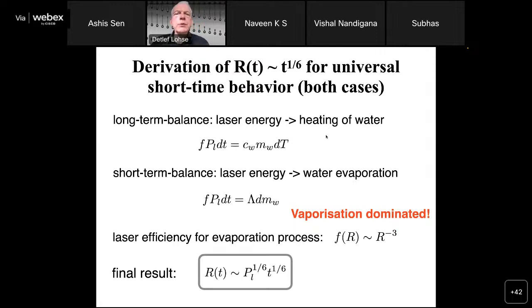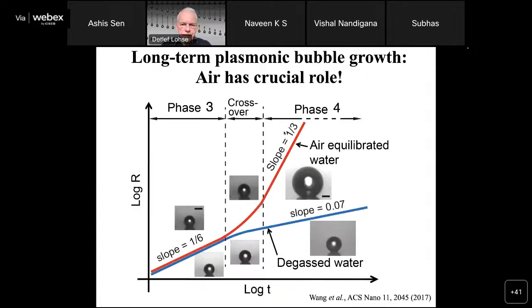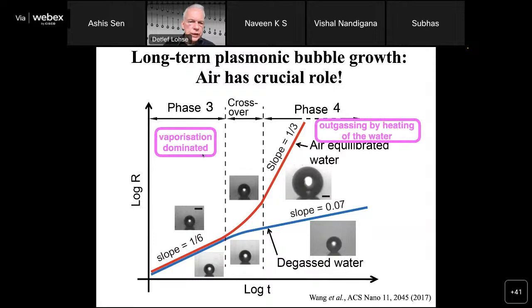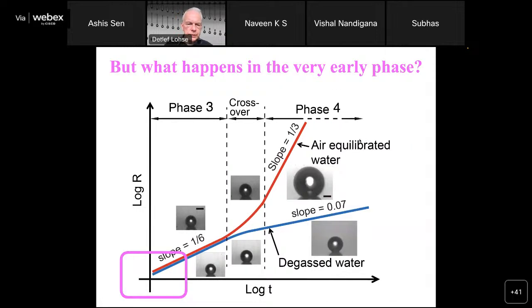So the question is, where do you use your laser energy for? Well, in the long term, it's for the heating of water, but in the short term, of course, it's for water evaporation, and then you get that the radius goes like t to the 1/6. This is this phase around here. So at early times, the radius goes like t to the 1/6, and then later for water with gas, the radius goes like t to the 1/3, or it's about constant if there is no gas. But the big question is now, what's happening? Well, this is what I explained to you. Here it's vaporization dominated, and here it's dominated by outgassing because you heat the water. But the question is, what's going on right here in the very, very early phase?